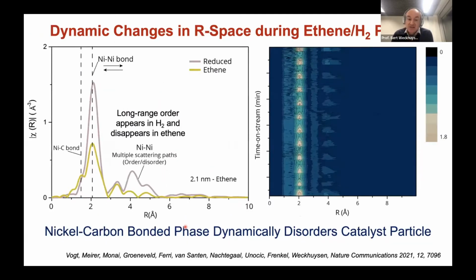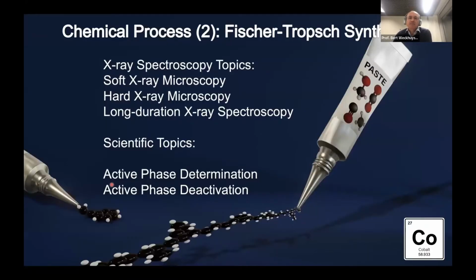Now, to focus more on this, we can also plot it in R space. Here I show you the reduced nickel in hydrogen and ethylene, and how it responds. Here you see the nickel-nickel bond, and here you see the nickel-nickel multiple scattering. And here I show you the different pulses giving hydrogen, CO2, or hydrogen, ethylene, in this case ethylene. So here you can show that the nickel-carbon bonded phase dynamically disorders, and we believe that it dynamically disorders also the catalyst particle. So this was my first part on CO2 hydrogenation and transient experimentation.